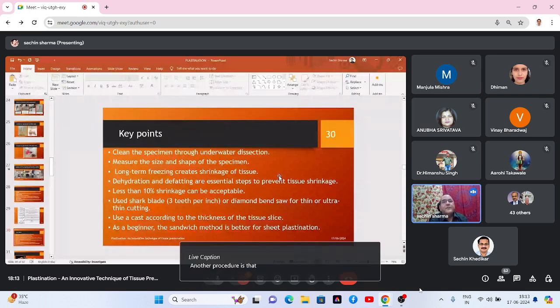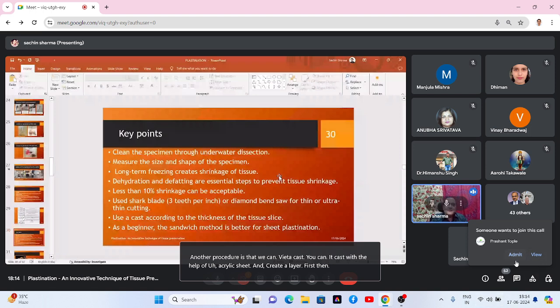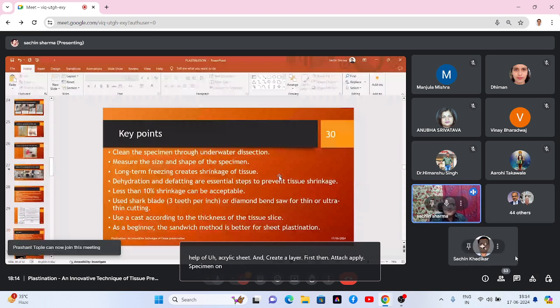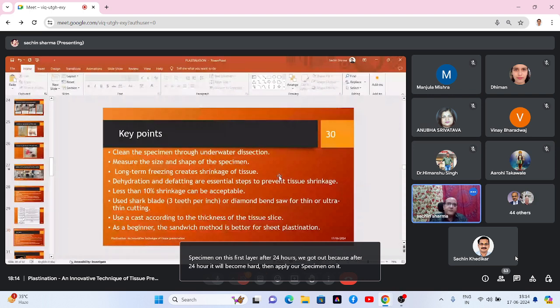Another procedure is that we can create a cast. We can create a cast with the help of an acrylic sheet and create a layer first, then apply a specimen on this first layer after 24 hours, because after 24 hours it will become hard. Then apply our specimen on it, and then again pour the second layer over the specimen, so that we can get a complete slice of specimen, plastinated specimen. This is called sandwich method. So for the beginners, sandwich method is very good for sheet plastination.